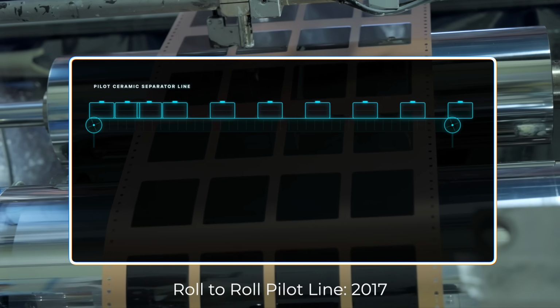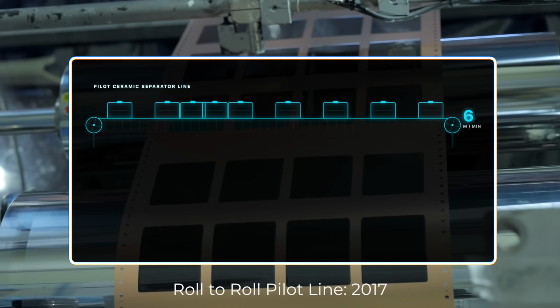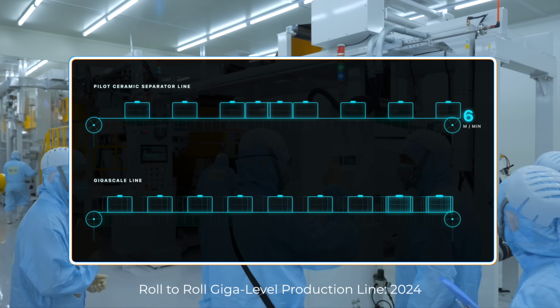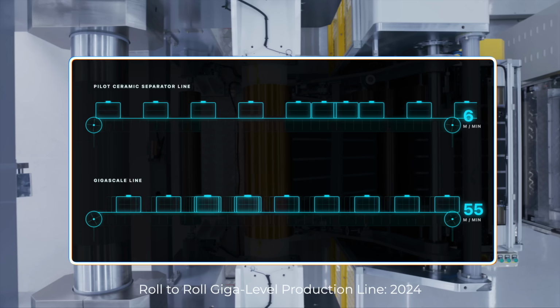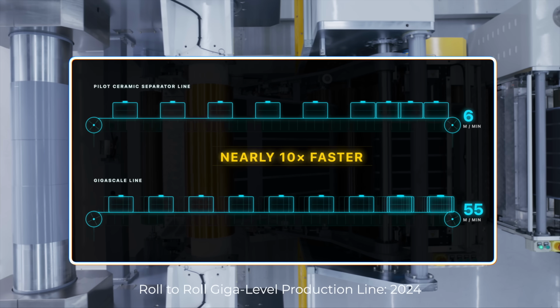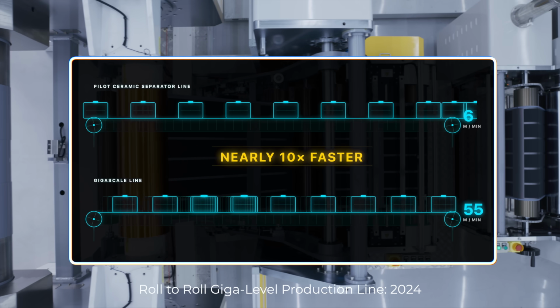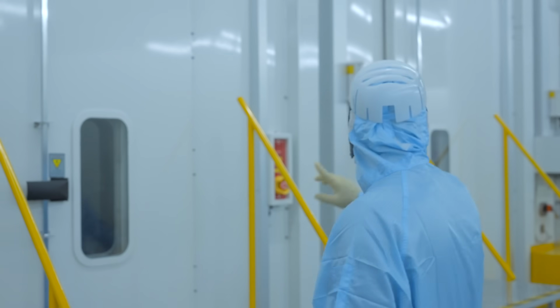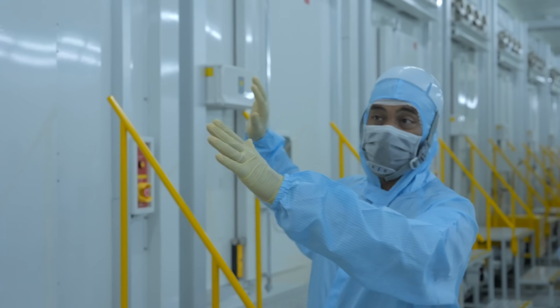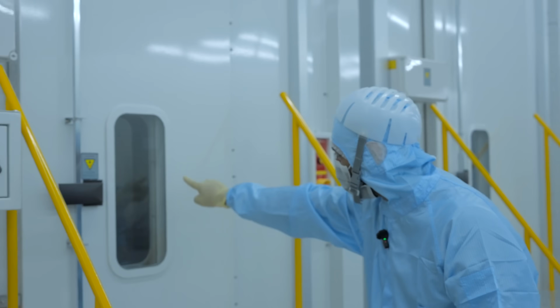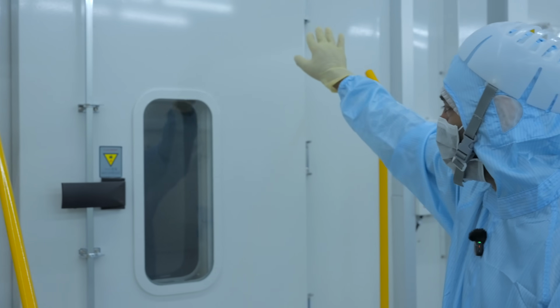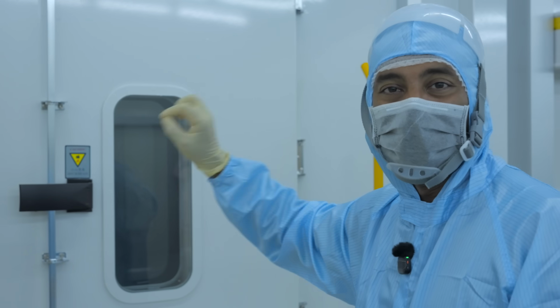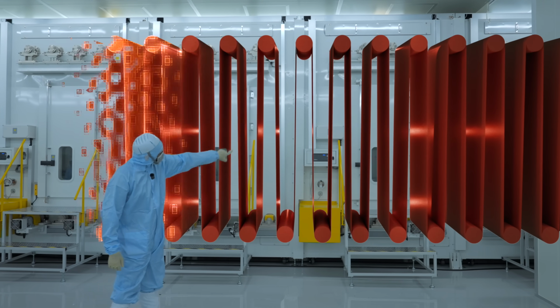ProLogium's pilot ceramic separator line runs at 6 meters per minute. Their gigascale line runs at 55 meters per minute, nearly an order of magnitude faster than any sintering approach could even imagine reaching. Then there's drying. This oven behind me is 24 meters long, but by the time this roll has snaked through, it'll travel 240 meters up and down.